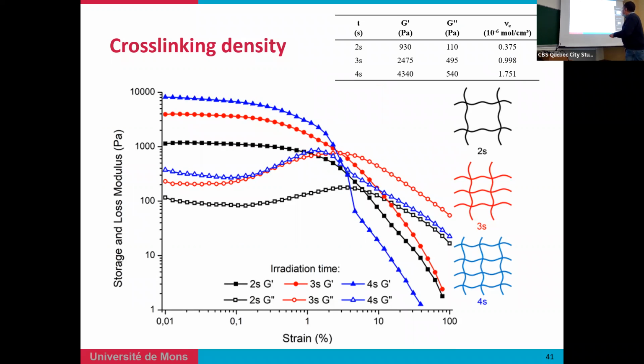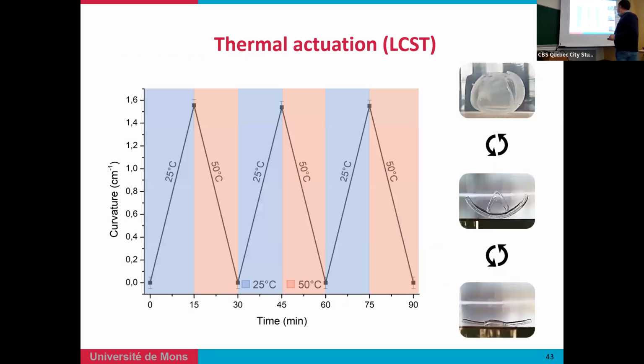This is shown here in the final product, by following the storage modulus against this photopolymerization time, particularly G prime related to storage. We can see that when you use a short polymerization time, you have a certain modulus that increases with polymerization time because you increase the crosslinking density, as shown here at 2 seconds, 3 seconds, and 4 seconds, where you obtain a highly crosslinked network at the end. Of course, G prime also increases thanks to this feature.